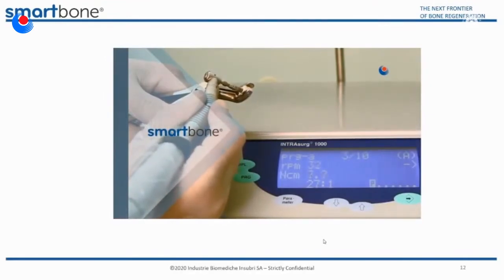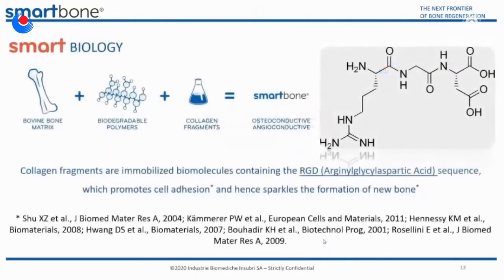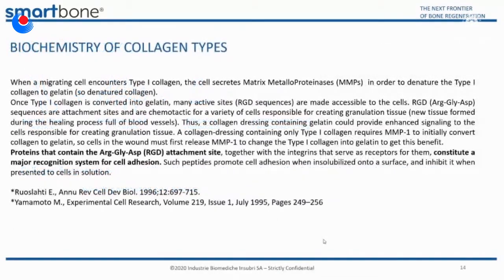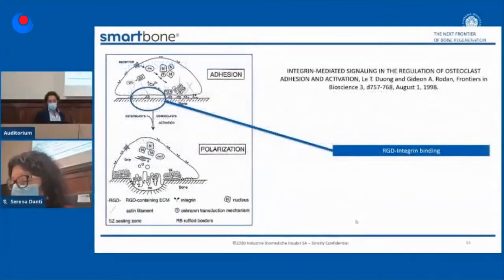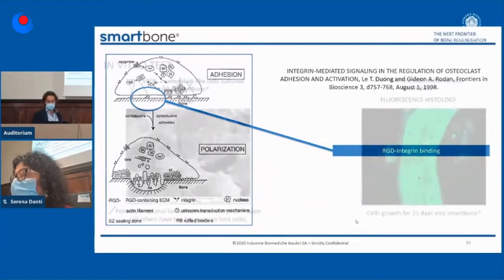So you can see that this material is very, very strong, easy to shape, easy to fix. About the biological aspect, we put some gelatin, so a material that contains the RGD sequence. In this case, the cells can connect immediately to the surface of the bone, especially osteoclasts that have to destroy the necrotic bone. The xenograft bone can connect immediately to the surface of the graft.